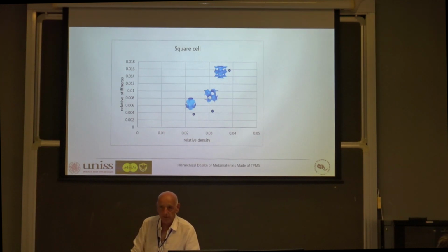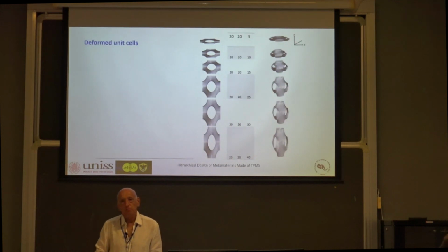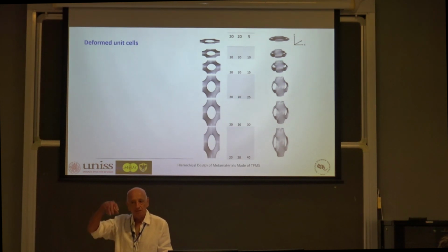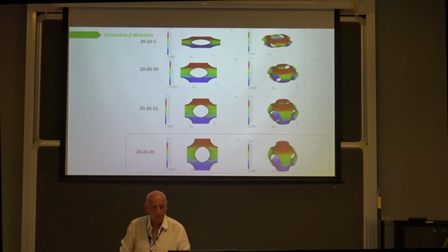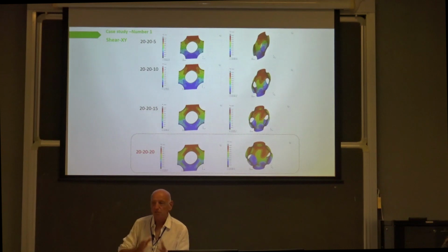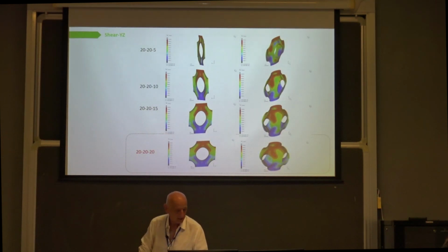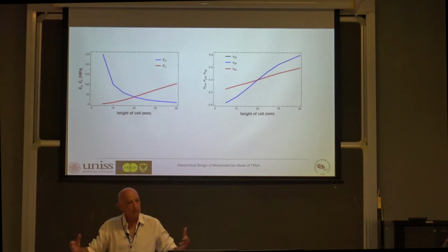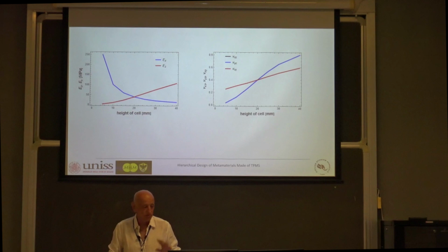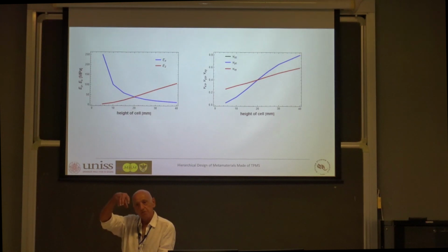Of course they are done for the same kind of thickness, but we are grading, so single homogenization is not enough. We have to investigate all kinds of possibilities. There are all these kinds of elongated cells, so we have to do extension in either one or the other direction, and shear in one or the other plane. We have to make all this investigation, and we come out with a bunch of results. This is interesting. For instance, the red curve on the left is the modulus in the direction where the cell is elongated, and the blue is in the other direction. You can see that as the cell becomes more and more elongated, it becomes stiffer. Why?